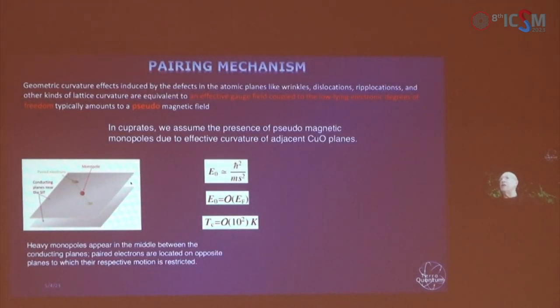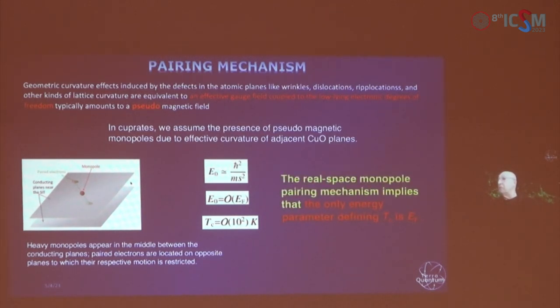And we can immediately introduce the pairing mechanism. This pairing mechanism appears because of the monopoles which should appear in between two conducting planes. And what is remarkable about this pairing mechanism is that the only energy parameter which comes in is the Fermi energy of electrons. And it means that basically the transition temperature, first of all the temperature at which Cooper pairs form, and then the superconducting transition temperature, can be actually much higher than it was believed before. So this is a real space monopole pairing mechanism, and it implies, I repeat, that the only energy parameter defining this superconducting temperature is the Fermi energy.